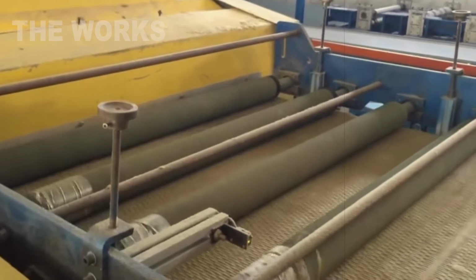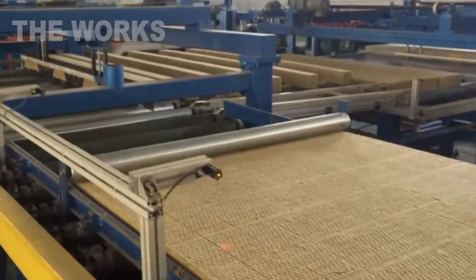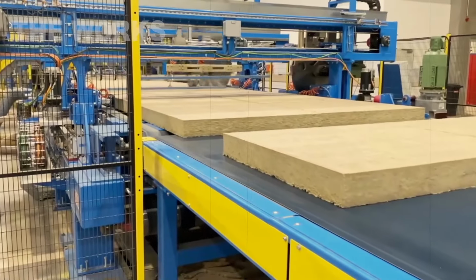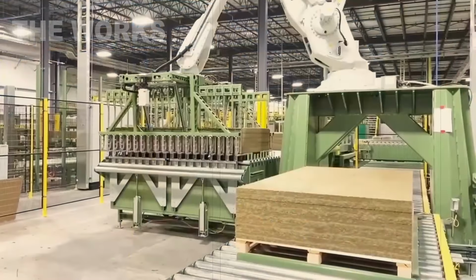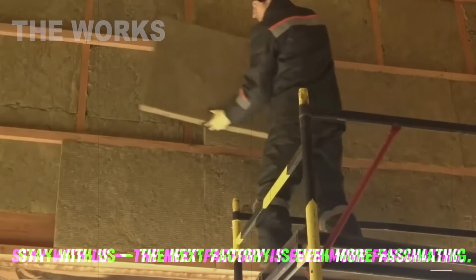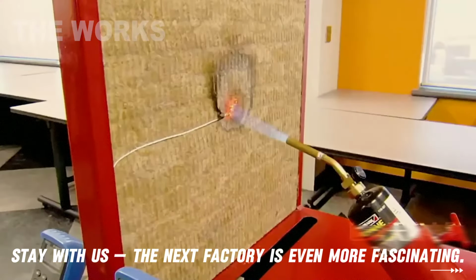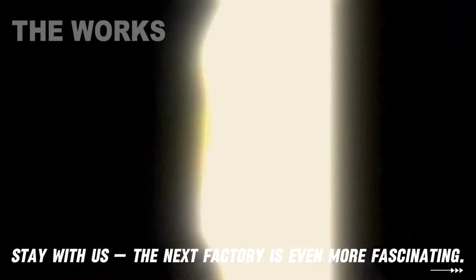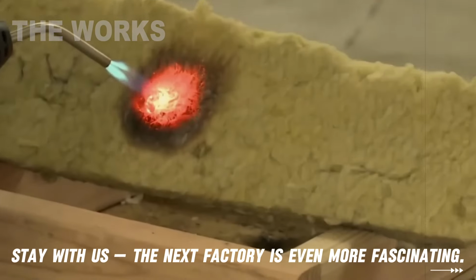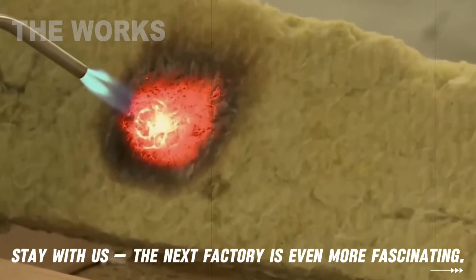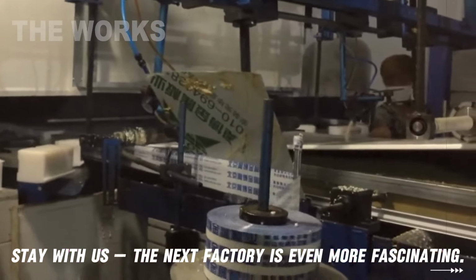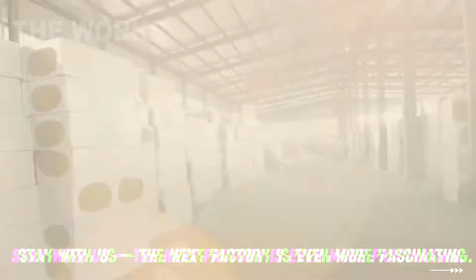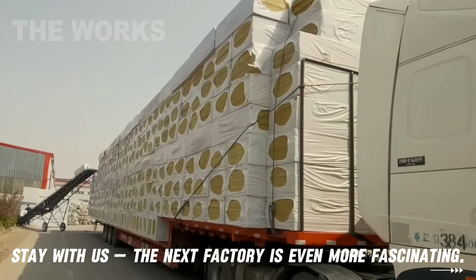The stone wool boards are ready now, but they've got to pass one crucial stage: quality control. Part of this process involves checking their hardness, where pressure tests are applied to make sure the boards can withstand mechanical loads without losing their shape or density. And since mineral wool is both fireproof and insulating, a fire resistance test is mandatory. Here, they use a flamethrower that scorches the surface to temperatures of around 2200 degrees, while a person can sit right behind it reading a newspaper, feeling nothing. After inspection is complete, the stone wool insulation boards are carefully wrapped in heavy-duty plastic film, then loaded onto trucks and shipped out to construction sites.